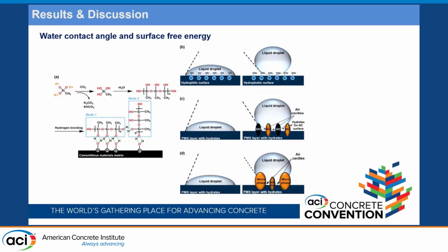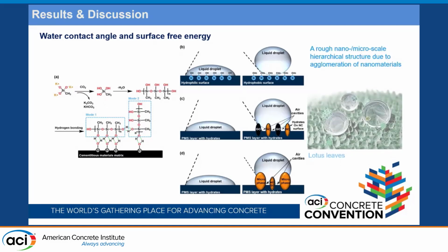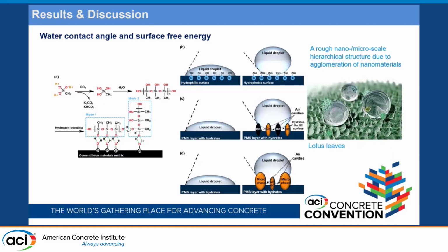We can learn from figure C. And during the hydration process, graphene oxide will also serve as the growth template for some hydration products, and then generate some larger hydrates. It will also help to enhance this micro nano hybrid roughness. So this looks like the lotus leaves. It's also a classic nano micro hybrid roughness.